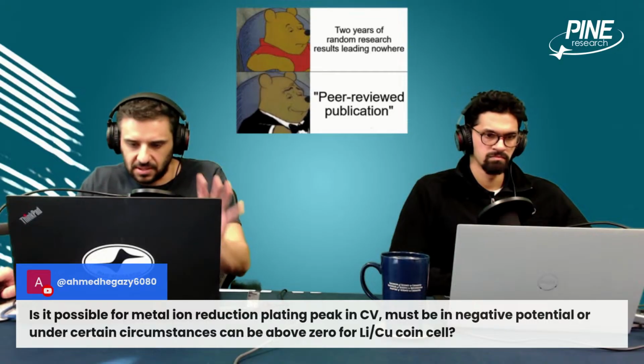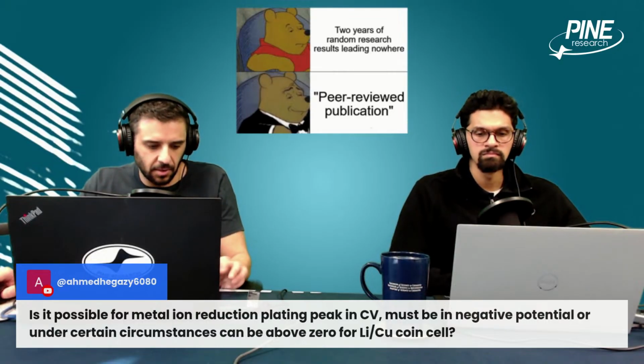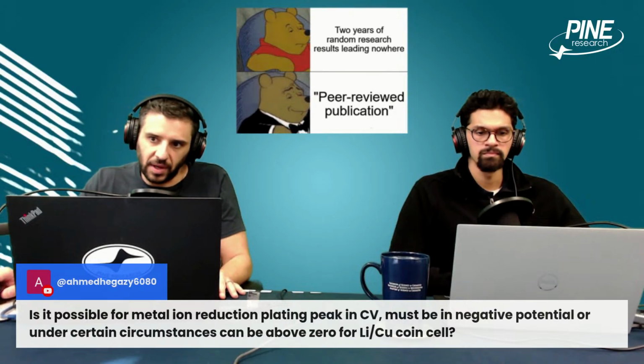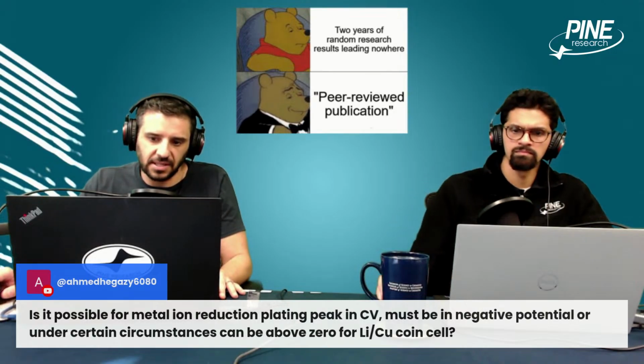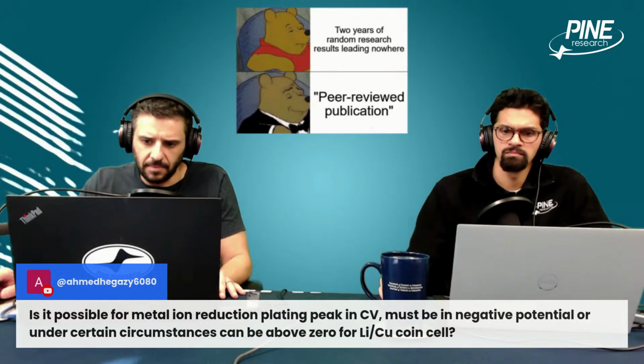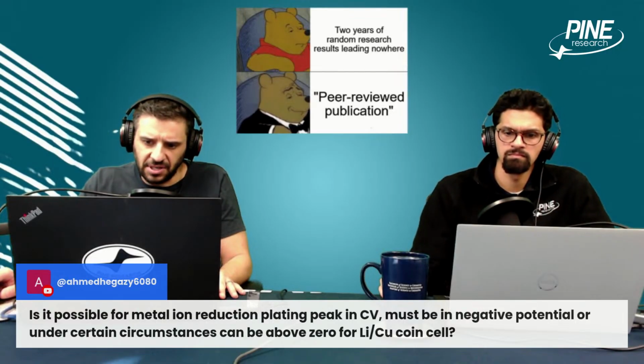And so the graphite reaction, for instance, occurs. I know you don't have graphite. This is a copper coin cell, but just as a basis of comparison, the graphite reaction occurs at like 0.1 versus Li plus, and that's about as low as it goes. Metal ion reduction plating peak must be in negative potential. Yeah,